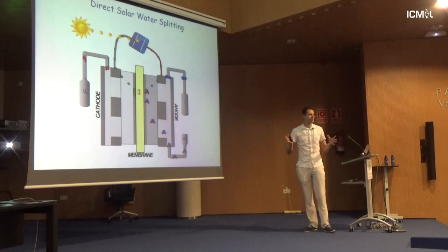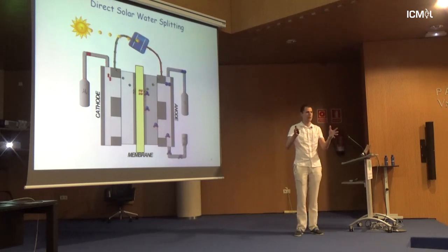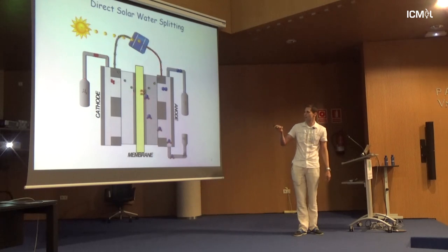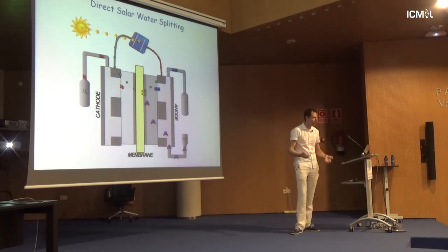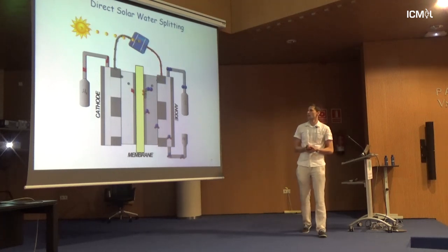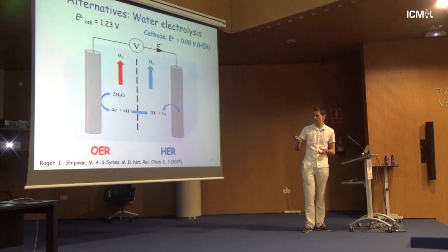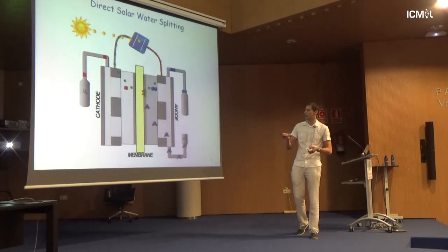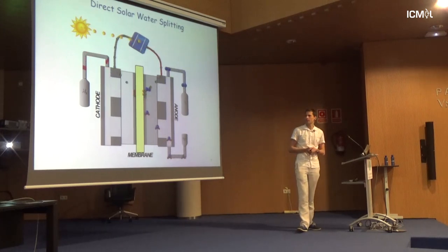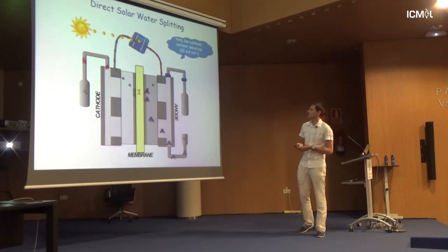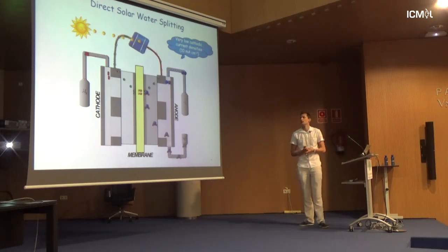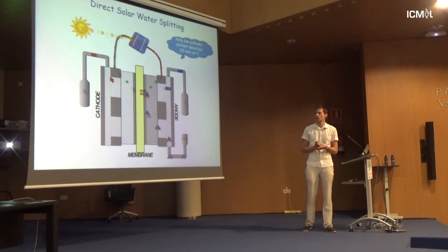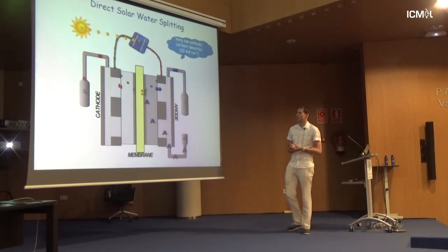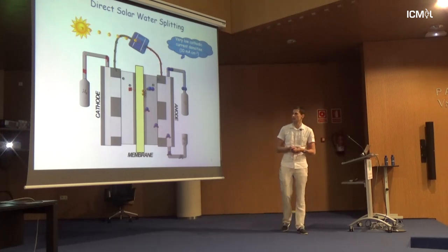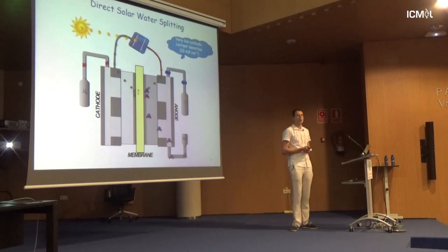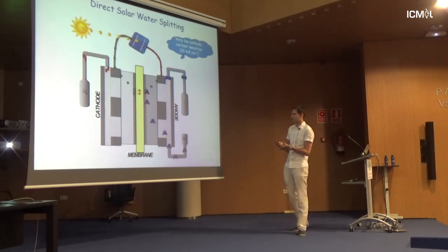So effectively, you have a very, very interesting system. You have two metal plates, then you have the more or less porous electrodes with your catalyst, and then you pump in your reagents, and then you collect your hydrogen and oxygen separately. So it's a very, very simple and trivial thing to do. So the problem is if we use solar cells, for example photovoltaics, then the current density you can achieve even from this quite sophisticated cell is relatively low. So what does it mean from a practical perspective?